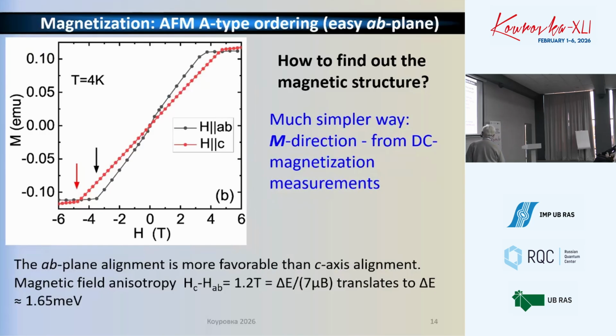You see that in plane, the magnetic field needed to saturate all spins, to polarize all spins, is smaller. Therefore, it's easy to polarize spins in plane, and therefore the spins necessarily have to lie in the basal plane, and it is a little bit harder to polarize magnetic moments when you apply the magnetic field perpendicular to the plane. So we deal with an easy plane antiferromagnet. The difference between the red and black curves immediately gives you the value of the anisotropy constant, which comes into the Hamiltonian when you analyze the properties.